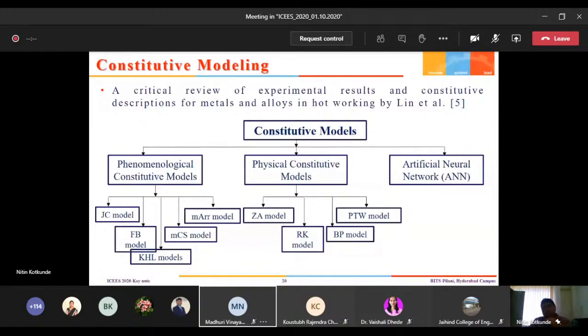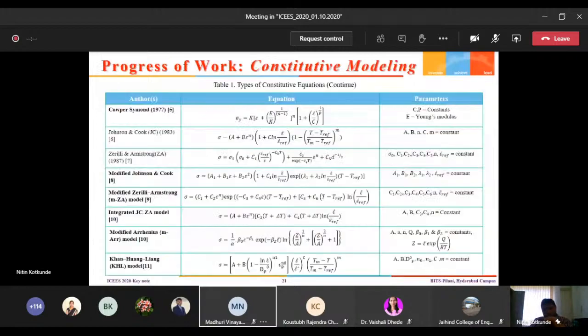So we have tested this material with very different constitutive models which are available in the literature, like Cowper-Symonds, Johnson-Cook is very popular. These are the many models. You can find them in popular finite element software like ANSYS, Altair, Abaqus. So these constants need to be calculated and given as an input for FE simulation. We have tested Cowper-Symonds, Johnson-Cook, Zerilli-Armstrong, modified Johnson-Cook, modified ZA, integrated JCZA, Arrhenius, KHL model.